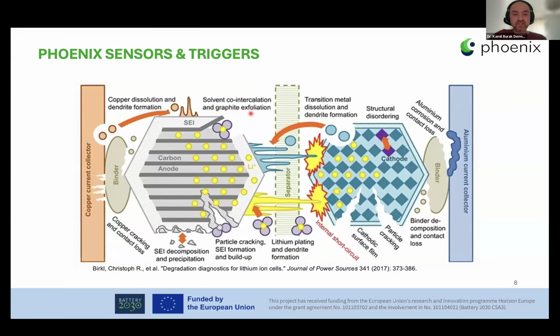Then solvent co-intercalation and graphite exfoliation can also happen at certain points. Since we are trying to put the larger-size solvents into the graphite anode, the graphite could exfoliate. When it comes to the electrolyte and separator side, mostly linked to the anode interfaces, lithium plating and dendrite formation can occur. If the dendrite growth is larger than expected, it can reach the cathode side, leading to internal short circuits and posing safety concerns in the batteries.